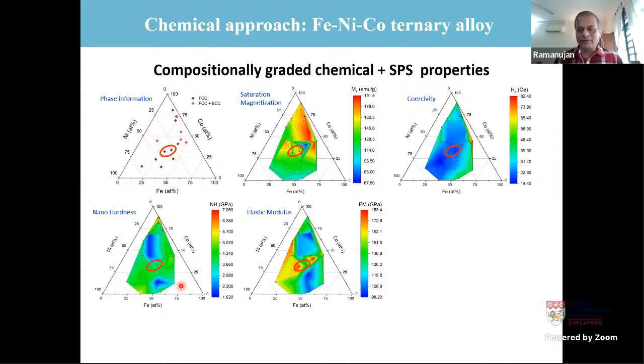Yes, the answer is yes. You have exactly said the right thing. But even within the iron, cobalt, nickel space, we do have a variety of crystal structures, because iron is BCC at room temperature, nickel is FCC, and cobalt is HCP. So even in this space, as you can see in this graph, we can identify some regions which are just FCC, other regions which are FCC plus BCC. When you have a two-phase structure, the mechanical properties are obviously different. The resistivity is also different compared to a single phase structure. Trying to model this would be a nightmare, but it's relatively easy to do with this technique.